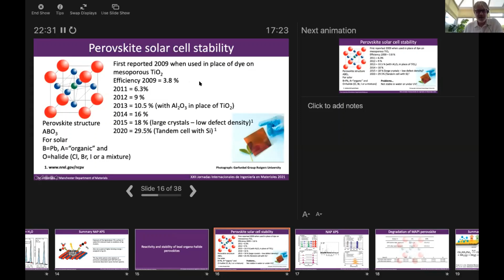The reason these materials have kicked up so much excitement and interest is because in 2009 the efficiency was 3.8%. Within 6 years the efficiency had been increased to 18%, by growing large crystals with a low defect density. This was a huge jump, especially when you compare it to dye sensitized solar cells, which these were basically a form of. The original dye sensitized solar cells hit a maximum efficiency of about 13% in 1999, and they've been there ever since. Then last year the group in Oxford made a tandem cell with silicon which had an efficiency of 30%. So we're actually getting into a position where we can compete with or improve on the efficiency of silicon solar cells.